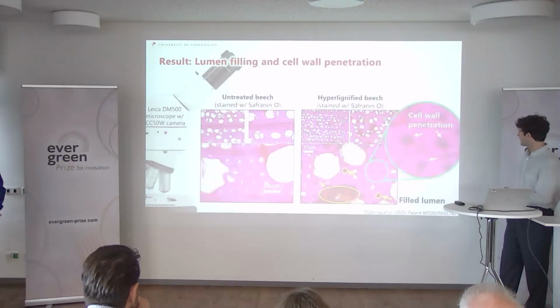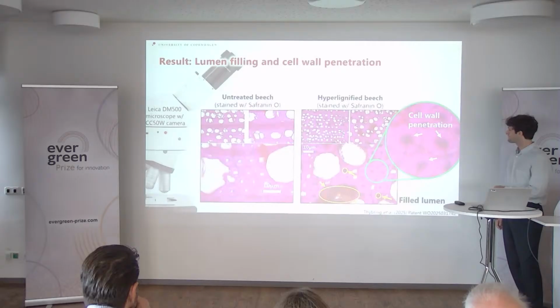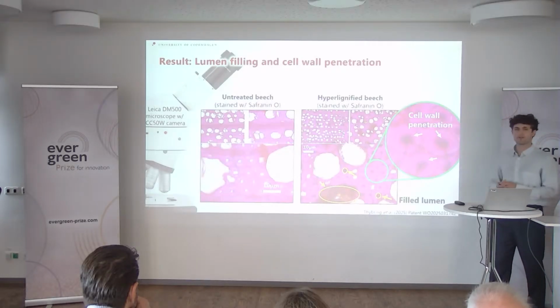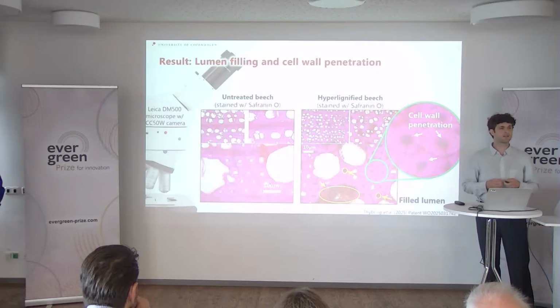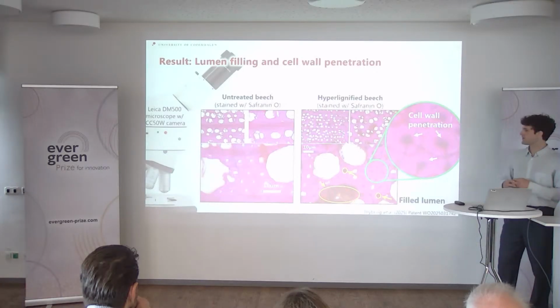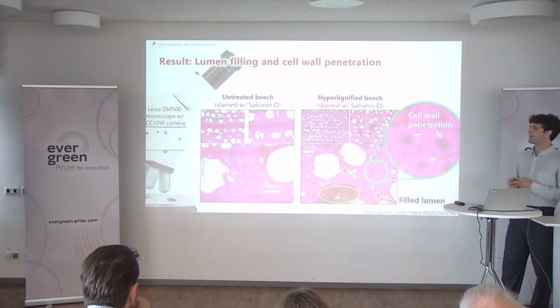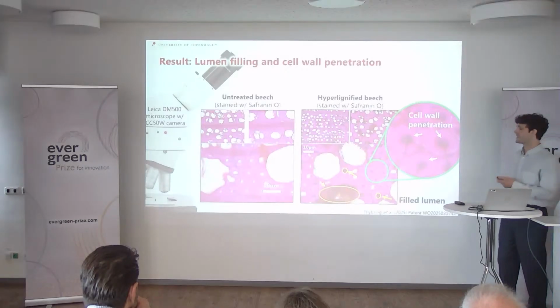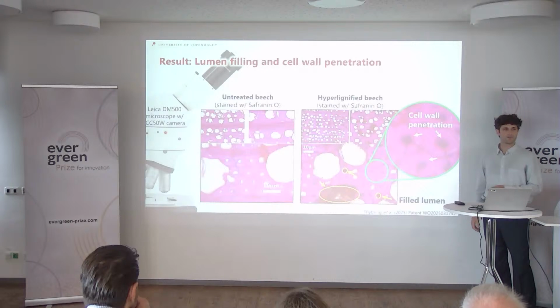But not only that, if we zoomed in, we could see there is a darkening around the cell wall, meaning that this penetration is not just at the surface or blocking. So we are modifying the structure, and we think that this is actually the key for the long-term durability to see.